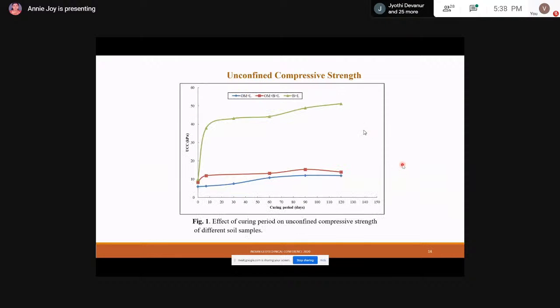Next is the effect of curing period on free swell index. For bentonite plus lime soil mixture, free swell index was seen to decrease, whereas in the case of bentonite, lime and organic matter mixture, the free swell was seen to increase and then decrease. Now coming to the strength result, unconfined compressive strength. These are the results plotted.